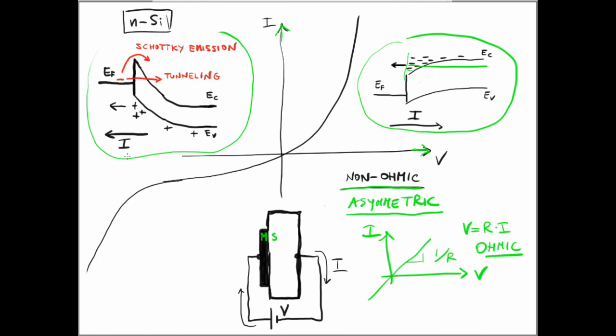If the bias we apply, though, is quite negative, what can happen at a certain point is that, as we can see here, the current can actually start to increase quite abruptly. And the reason is that the electrons in the metal at a certain point may be able to either tunnel through this effectively nearly triangular barrier, or they may acquire enough thermal energy to actually go around the barrier that they see in front of them. And this is what we call a Schottky emission that we will discuss in the next chapter. This is also the reason why sometimes you may see that this type of contacts, MS contacts, are also referred to as Schottky contacts or Schottky device.